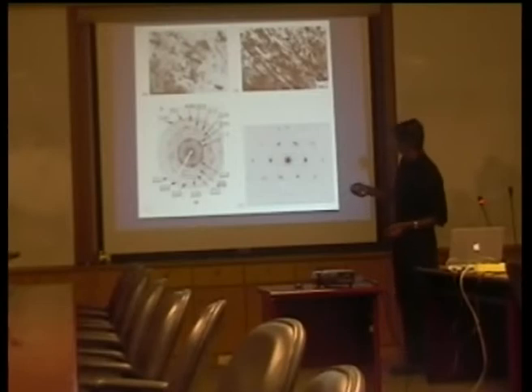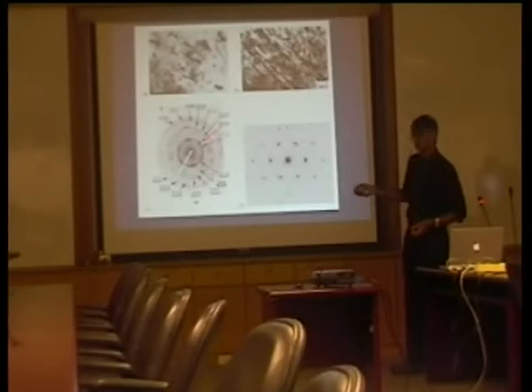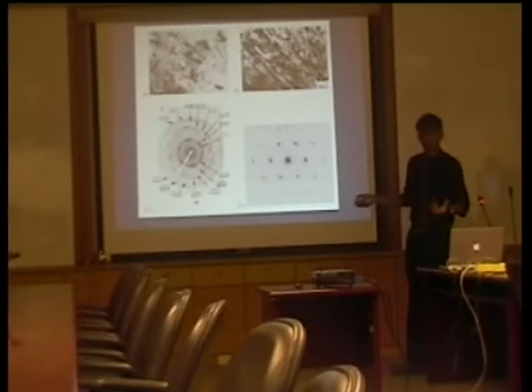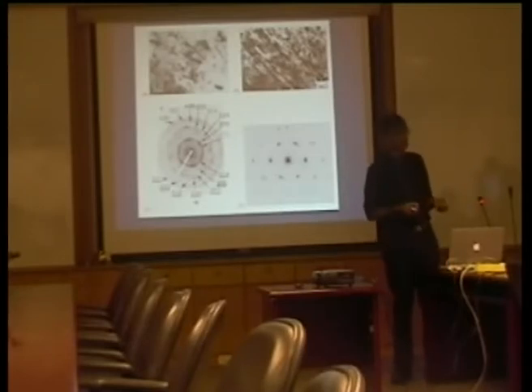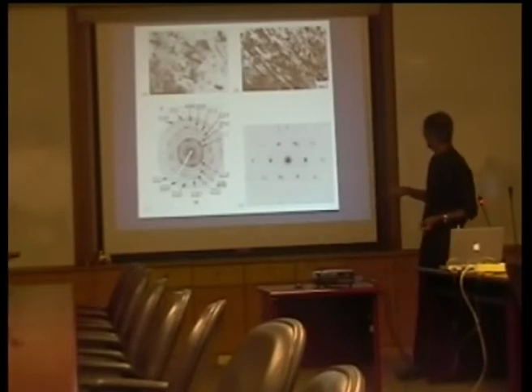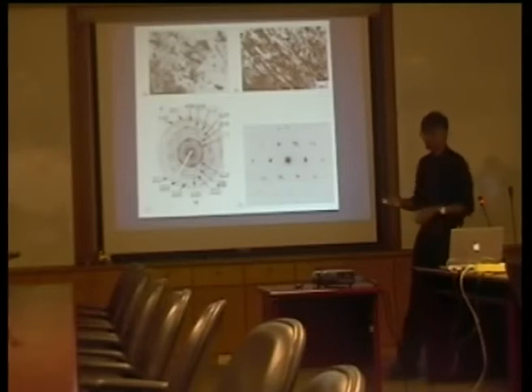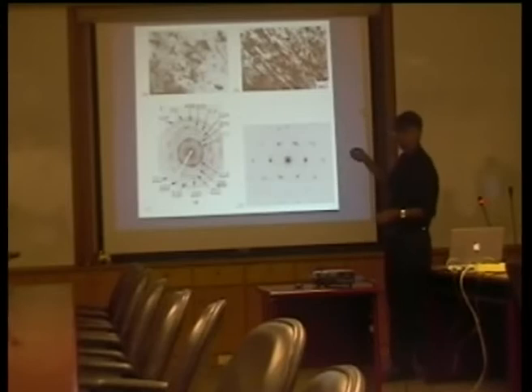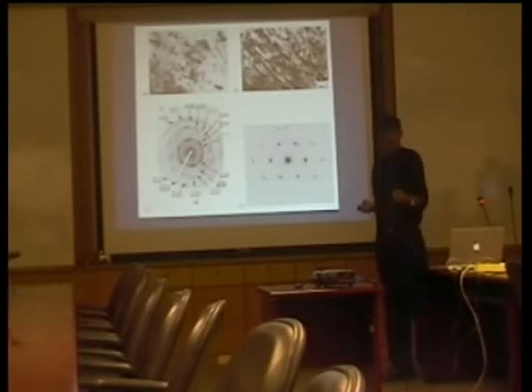And if you look at the orientations of these grains, they are random, because in the electron diffraction pattern you've got circles. Yeah, that means you've got grains in many, many different orientations. It's like a powder diffraction pattern. But if you look on this section, then you've almost got a single crystal here. Yeah? This is a spot pattern, meaning that there isn't much misorientation between these crystals. So it is a strongly crystallographically textured sample, because deformation produces texture.